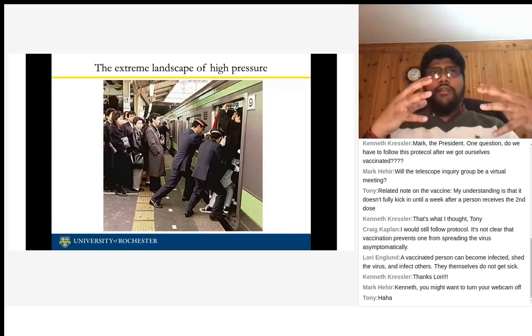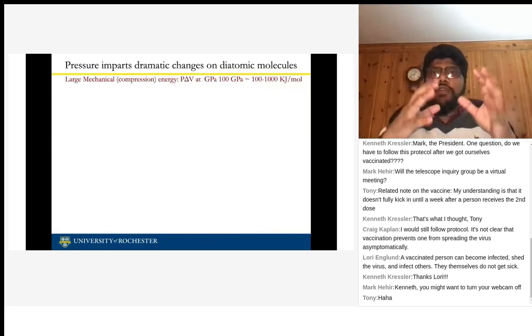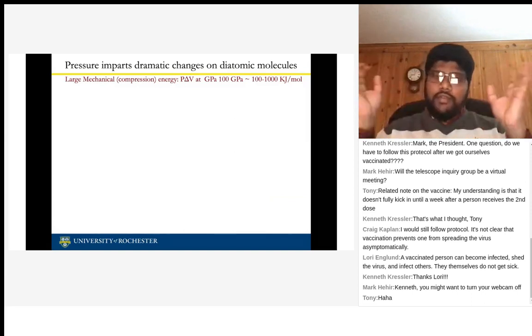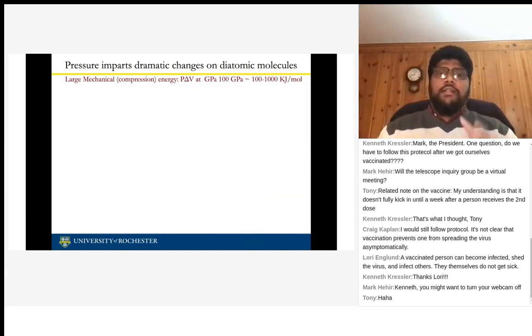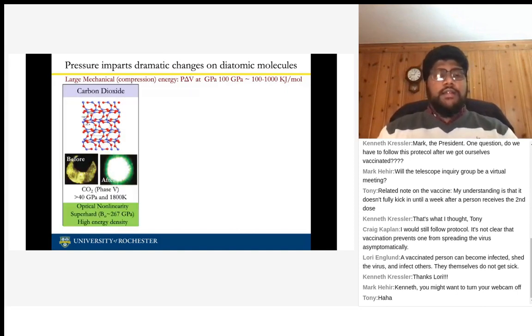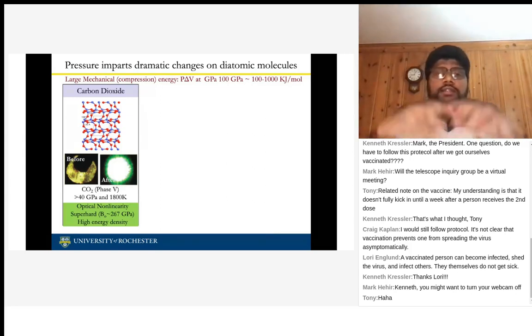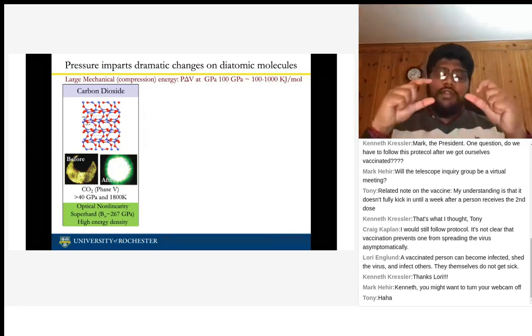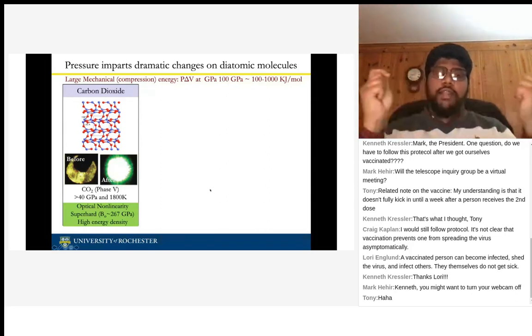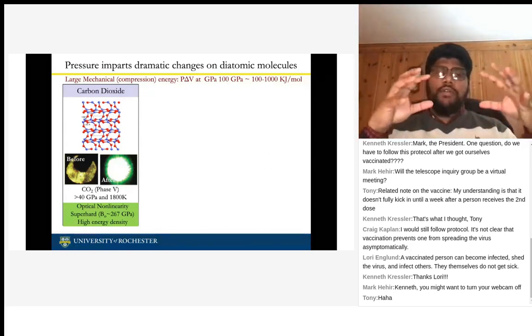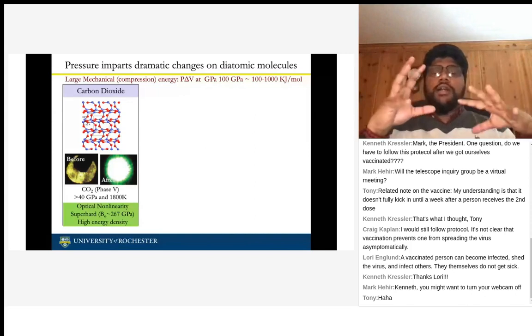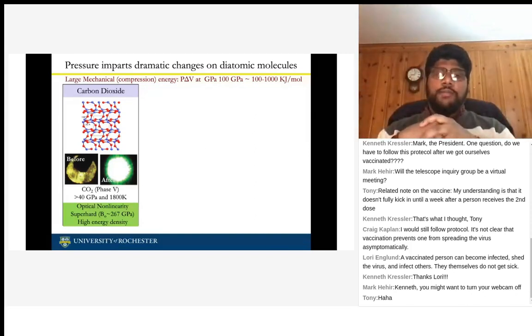So if you go from, let's say, one atmosphere to 3.6 million atmospheres or even higher, the materials that we know at ambient conditions don't really exist the way they should. For example, carbon dioxide is a greenhouse gas. But if you subject it to really high pressures, these synthetic conditions break the double bond between carbon and oxygen and make it single bonded, just like a diamond structure, a CO2 structure.